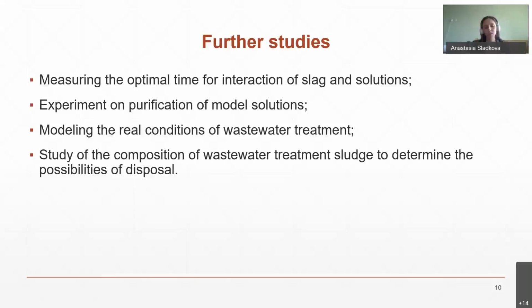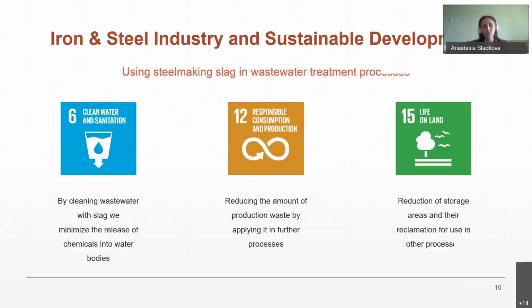In order to successfully use steelmaking slag in wastewater treatment processes, it's necessary to carry out several tests in the future. Firstly, we need to measure the optimal time for the interaction of solution with slag. And secondly, an experiment on the purification of a model solution with several components needs to be done. And also, we need to study the composition of the sludge obtained after treatment to determine the possibility of its disposal. And that's also important for using the slag in further processes.